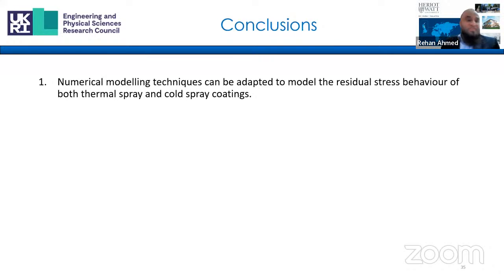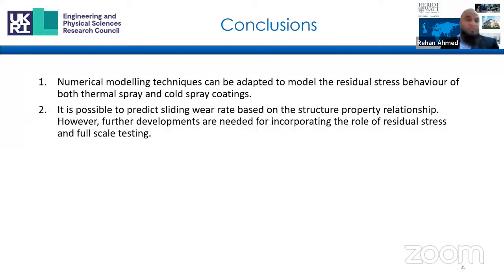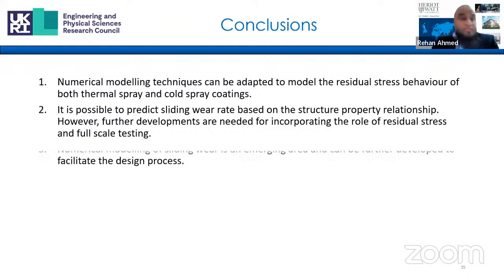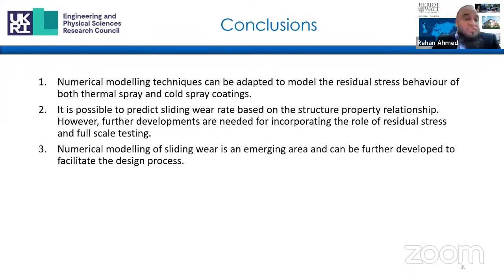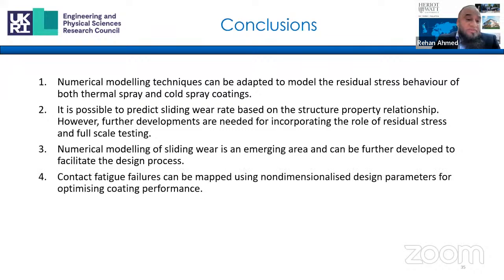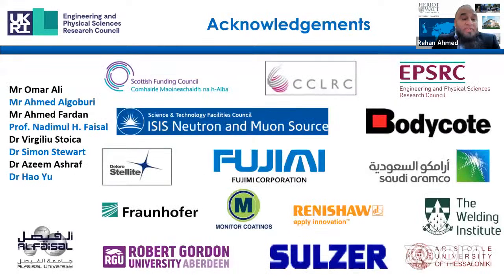So in conclusion, we can say that numerical modeling techniques can be adopted to model residual stress behavior of both thermal spray and cold spray coatings. It's possible to connect all these models and link structure property relationships and incorporate the role of residual stress in the coating development. And numerical modeling of sliding wear is an emerging area and can be further developed to facilitate the design process. And contact fatigue failure modes and mapping can be used to optimize the design process.